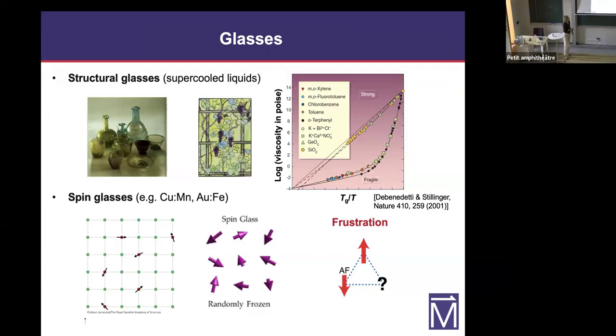Another well-known example are spin glasses, which are alloys in which a relatively small percentage of magnetic ions, such as manganese and iron, are mixed randomly in a lattice of good metals like copper and gold. But because of the random distribution, they are not able to order, so they get stuck again in random configurations or metastable states. What is striking about glasses to me is that their phenomenology is very similar, even though obviously the microscopic mechanisms that underlie their dynamics are very different. So this was a difficult problem to solve for many years.